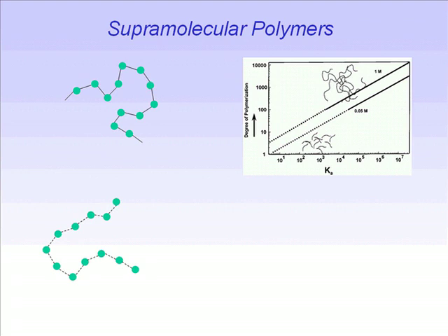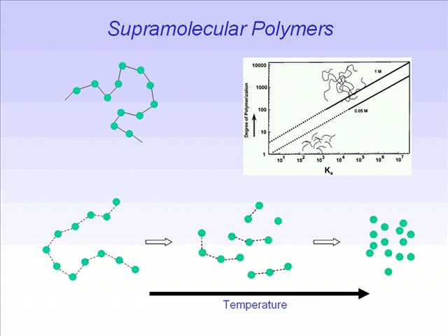Now, what is interesting about this class of systems is that unlike covalent polymers, where each repeat unit is linked by a series of covalent bonds, in non-covalent interactions, these are hydrogen bonds or multiple hydrogen bonds that hold them. What is unique about this kind of structure is that the properties of the system are strongly correlated with several of the properties of the solution itself. For instance, as you increase the concentration of the monomer units in the solution, the length of the chain continuously increases.